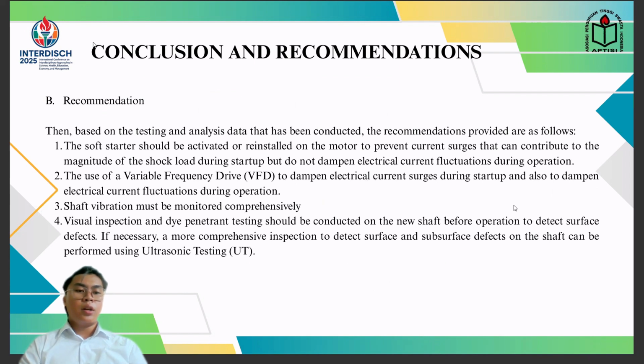And this is the recommendation. One, the soft starter should be activated or reinstalled on the motor to prevent current surge that can contribute to the magnitude of the shock load during startup, but it does not dampen electrical current fluctuation during operation. Two, use a variable frequency drive to dampen electrical current surge during startup and also to dampen electrical current fluctuation during operation. Three, shaft vibration must be monitored comprehensively.